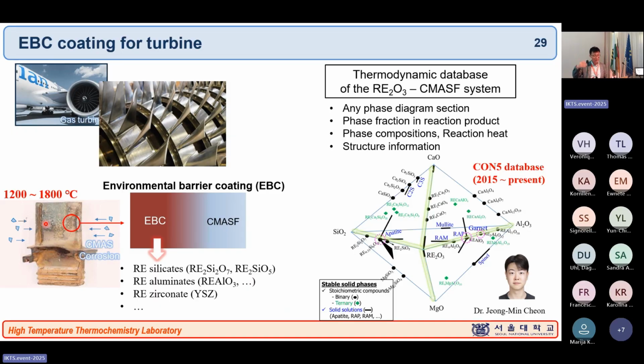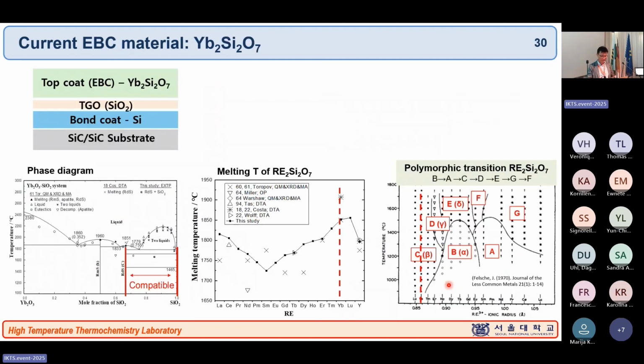But unfortunately, the turbine engine actually operates high in the sky. There's always dust like CaO, MgO, Al2O3, SiO2. If you go to a volcanic region, there's also additional FeO dust, and that forms liquid slag at about 1400 degrees Celsius, and that can damage the refractory material on the turbine, the EBC coating, sorry. So we made a special database now for the rare earth oxide with all these important slag components.